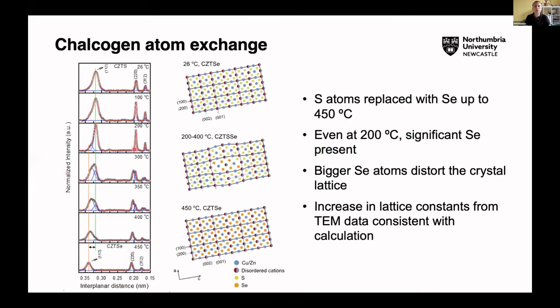So essentially, this is what we see. In the range 26 to 450 degrees, these are extracted diffraction patterns. We see the system evolving from the CZTS, which is the sulfur system, these nanoparticles, to CZTSe nanoparticles. So we replace nearly all the sulfur with the selenium, and that causes some lattice distortion, and we end up with this at 450. And these lattice constants are consistent with what we see from our XRD data as well. So that's kind of nice.